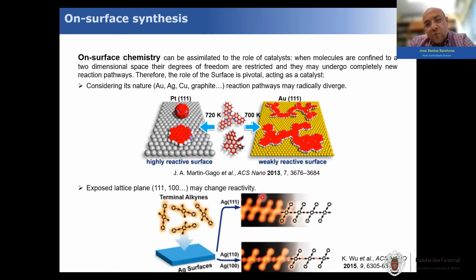In the first case, what we got is these polymers with this butadiene linker, whereas in the other less compact lattices, what we got is an organometallic polymer where these alkynes are coordinated by these silver adatoms that are taken from the surface.